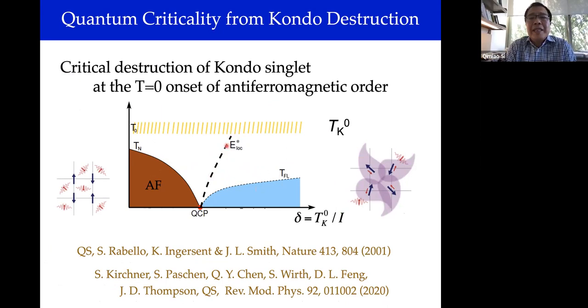And it delineates the regime where the system is flowing towards a small Fermi surface ground state, and the regime where the system is flowing towards a large Fermi surface ground state. So that's so far the most direct experimental means by which the E star scale has been measured.